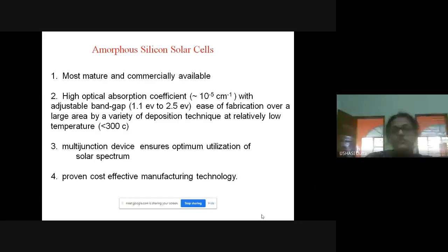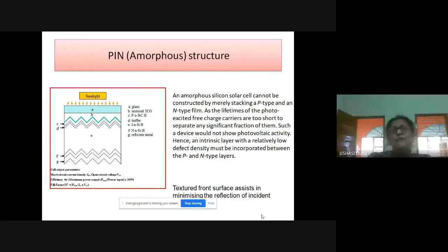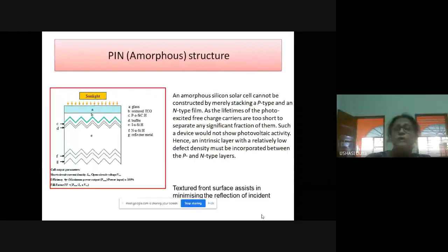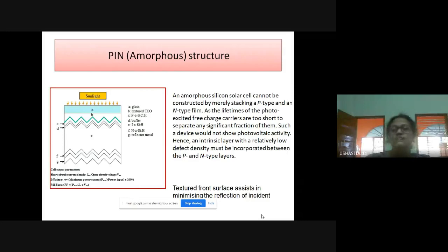Here is the basic PIN structure. Actually, amorphous silicon contains the PIN structure, and an amorphous silicon solar cell cannot be constructed by merely stacking a P-type and an N-type film, as the lifetime of the photo-excited free charge carriers is too short to separate any significant fraction of them.